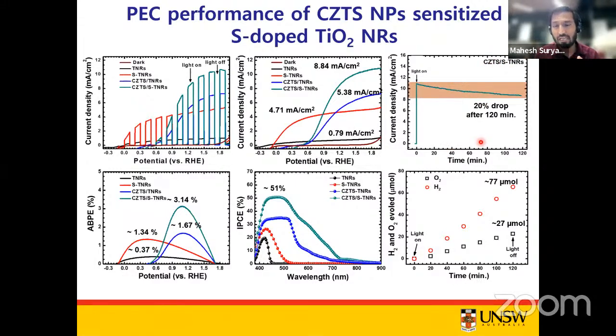Again, the reason is because, as I explained in my previous slides, the sulfur-based compounds are not stable in the aqueous electrolytes, and hence there is a slight decrement in the photocurrent density value, which needs further research to stabilize these compounds.